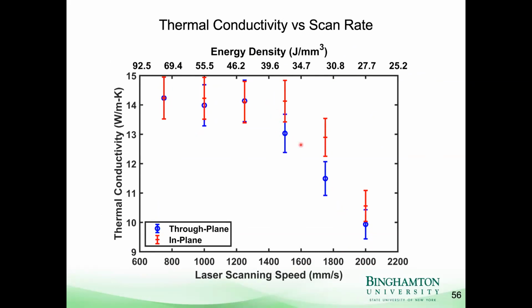And the reason for this, when you're not printing at optimal process parameters, the laser melting doesn't fuse neighboring layers as well together. There's maybe more grain boundaries and defects at the interlayer connections, and so that lowers the through plane conductivity more than the in plane conductivity.